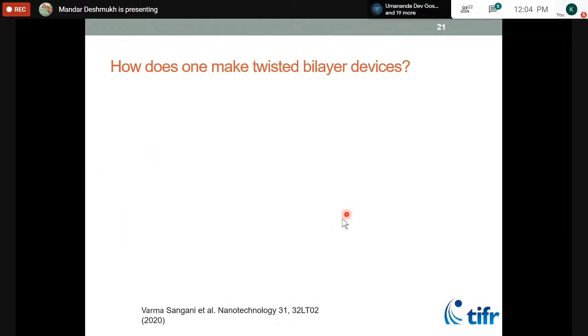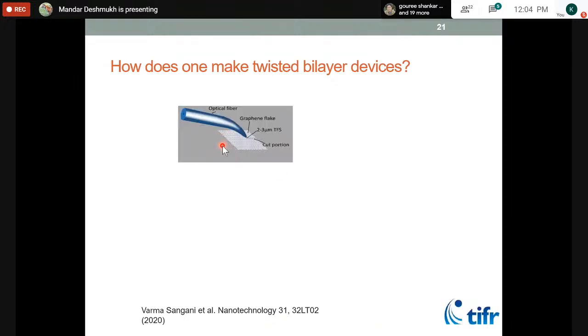Okay, so now, I'm going to end in a couple of slides, how does one make something like a twisted bilayer? Many groups follow different techniques. We have developed our own method to make these kind of devices. Because we want to realize layers which are rotated by a precise angle like 1 degree, you start with one sheet of graphene, and you cut it with what you can think of as a scalpel, which is sort of what we figured out.